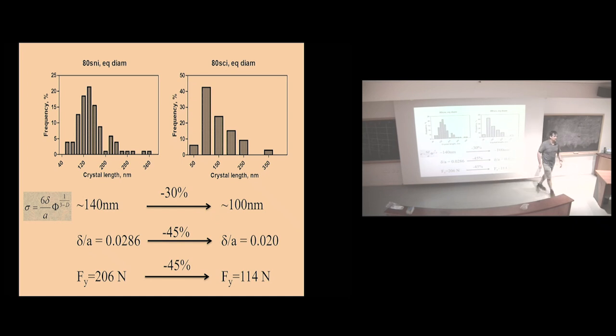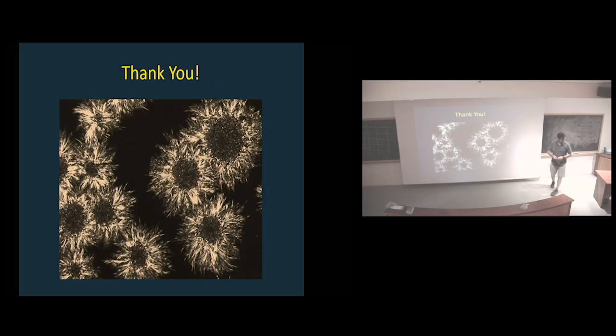It makes sense, right? I mean, it would be nice if it was controlled by one. What I'm saying is that tomorrow I do this experiment in another system, and it'll probably be a different behavior. But at least you got a framework to understand what you're doing. Maybe you should be messing around with the interfacial tension by adding surfactants. And so you add a little surfactant, you can change things dramatically. Why? Because you're changing the interaction between the crystalline nanoplatelets. At least it allows you to think a little bit, even if not try to predict. You would hope that it's predicting. And so that was the last thing at the end.